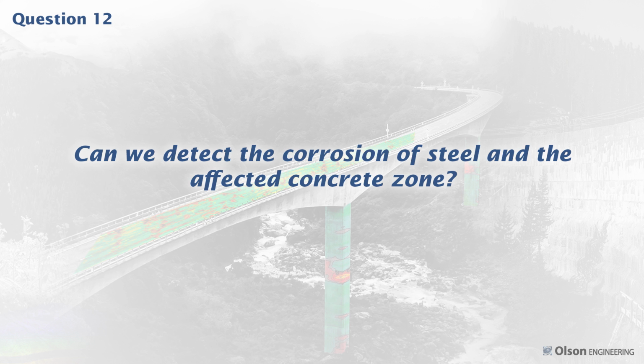Can we detect the corrosion of steel and the affected concrete zone? Well, again, that's pretty much what I just answered in the previous question. You cannot directly detect the corrosion with impact echo type testing. You can very easily detect the cracking that the corrosion results in.